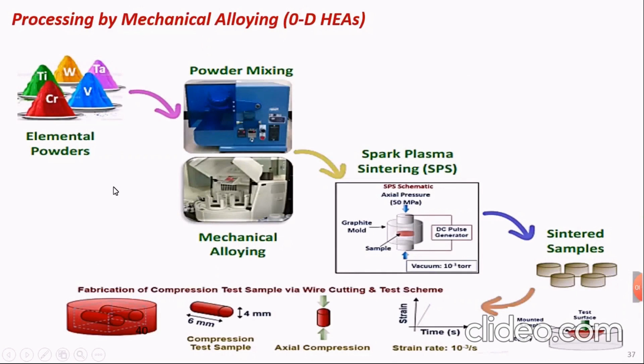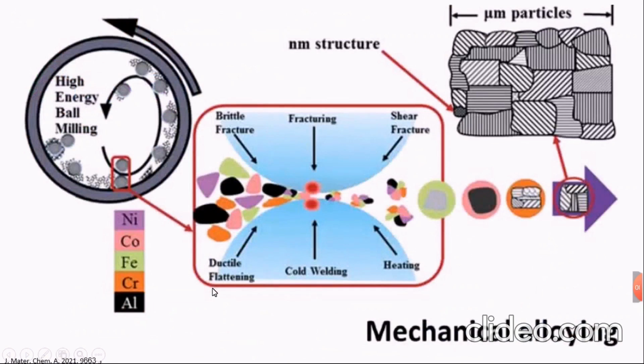First is to fabricate zero-dimension high entropy alloys by mechanical alloying. You have to follow the steps of powder metallurgy, which is powder mixing, sintering, compressing and so on. Here is an example of mechanical alloying. This is a high energy ball mill in which the particles strike together. So there is a kind of fracturing and cold welding that occurs. So the particles are combined together under this interaction in the high energy ball mill, for example in the high entropy alloy of nickel, cobalt, iron, chromium, or aluminum.